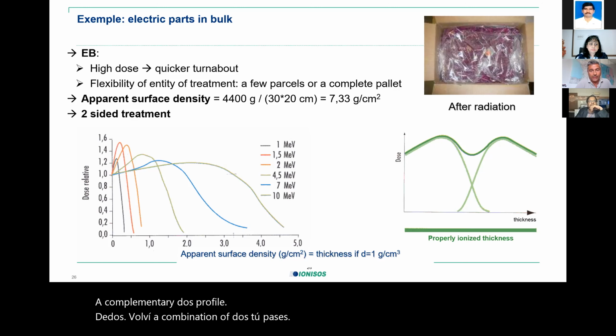As a rule of thumb, the maximum surface density that we can treat is around 7.5 grams per square centimeter, due to the limited penetration capacity of the electrons. Also, because of the way the electrons deliver the dose in depth, we will have some non-uniformity in the dose inside the product. This means that if we are targeting a minimum dose of 100 kilograys, because it's the dose that we need to achieve the desired gel percentage content, we will have other parts in the box that will reach a higher dose, in this case 163 kilograys. This means that we will need to check that the maximum dose is also acceptable for the product, and that the properties of the products are homogeneous enough. It's an important point in the process.